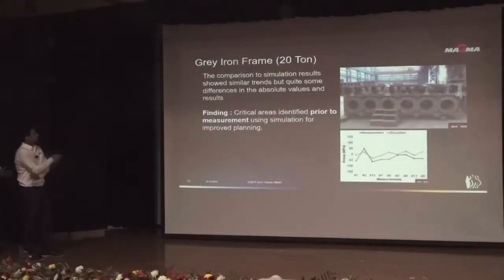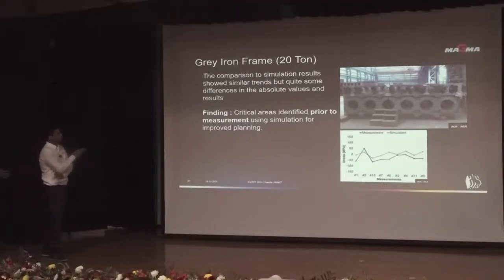As we compare the simulation results, there is a similar trend, but quite some difference in the absolute values of the results. But the finding was that the critical areas identified prior to measurement. So for the measurement using simulation, we planned before where we are going to put them.